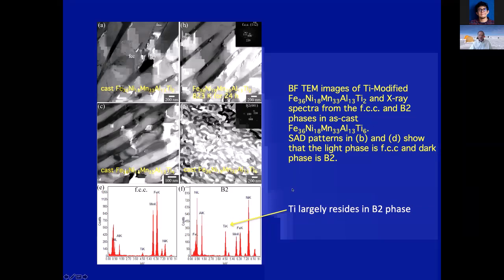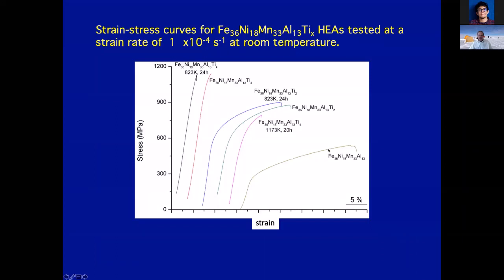So if we look at the mechanical properties, this is the material with no titanium, and then as we add more mass in the titanium, the yield strength goes up, but the ductility goes down. So again, there's a trade-off between ductility and strength, and that's plotted here. You can see the yield strength plotted as both the lamellar spacing to the -1/2 and to the -1. They're fairly similar. It's hard to tell the difference between them.